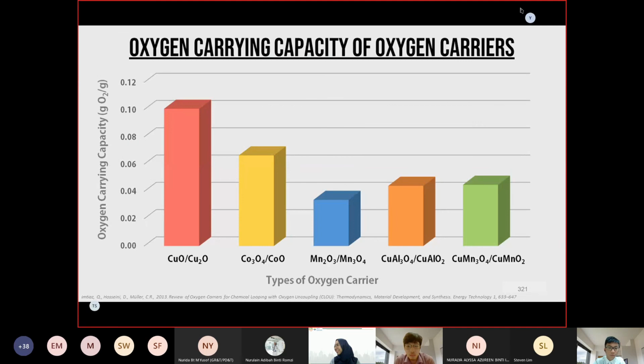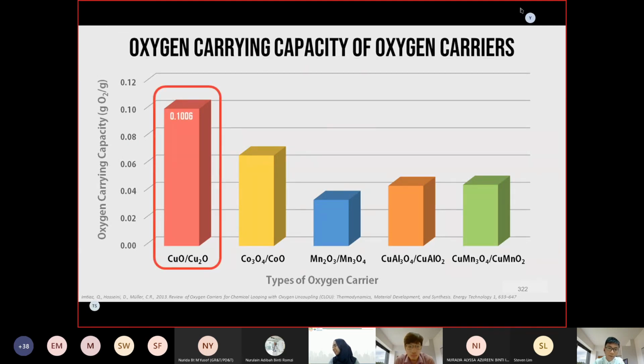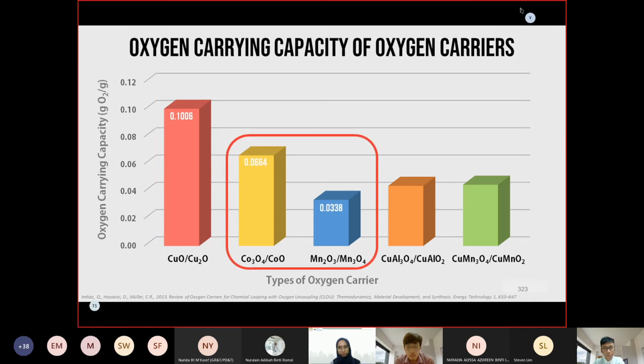Look at this graph. It is undeniable that copper oxide is the best oxygen carrier candidate, where it shows the highest oxygen carrying capacity among all. Every single gram of copper oxide could carry 0.1 gram of oxygen from the air to the fuel reactor. In this same graph, there are also cobalt and manganese-based OC, but their performance is not as good as copper-based OC.